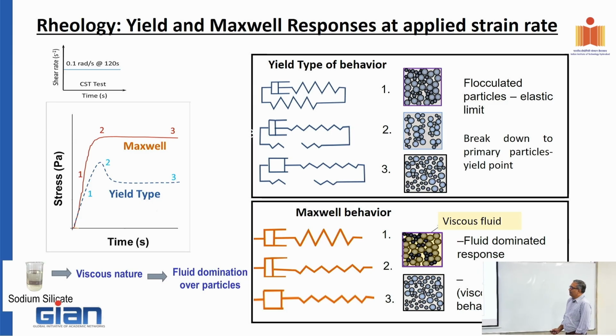But look at what happens in the Maxwell behavior. The resistance continuously builds up to the peak and then it stays constant. Now, if I was to idealize the yield type behavior, this is how we would idealize this. Basically, you would use a Kelvin type of model where you have a dashpot in series with a spring and then a spring that is shunted in parallel with this. So what happens if I pull this setup here? At some point, this spring breaks and then it continues to flow, right?